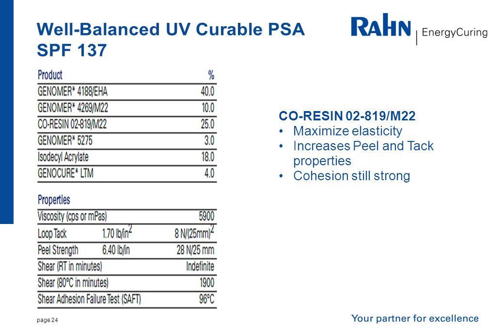As we look at our final well-balanced formulation, we see everything previously discussed all come together. Our elastomer components are now balanced with the addition of Tackifier Co-Resin 02-819. It helps to maximize elasticity, increase peel and tack properties while maintaining strong cohesion. As a result, we get a balance of good peel strength, 6.4 pounds per inch, loop tack, 1.7 pounds per inch squared, an indefinite shear at room temperature, decent shear at 80°C, and a SAFT failure at 96°C. Overall, a good starting point formulation for a well-balanced PSA.